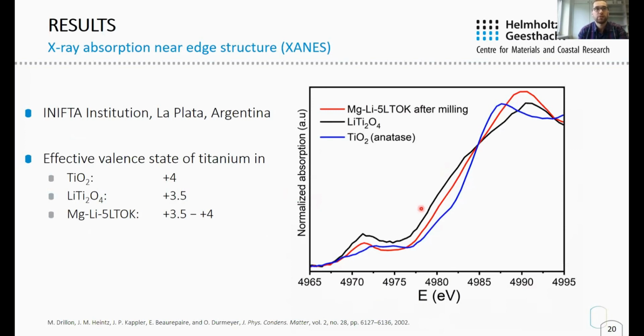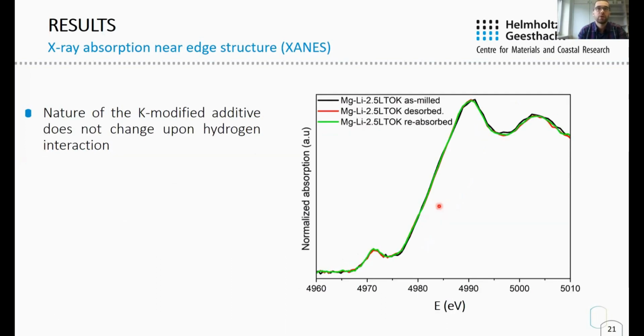Comparing the references with the sample, the absorption edge is positioned at higher energies with respect to lithium titanate. So it's showing that titanium has an oxidation state between 3.5 and 4 in our sample. So I should investigate the potassium containing phases which have an oxidation state between 3.5 and 4.